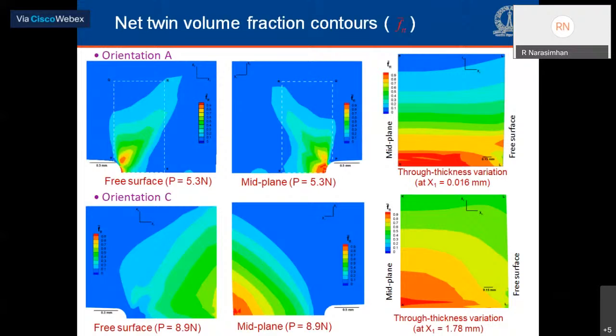And we note again that in A, the C-axis is along the normal to the flat surface of the notch, C-axis along the thickness direction. So if you look at the top panel, you can see that the twin volume fraction is developed in a roughly rectangular region emanating out from the notch root. And there's not that much thickness dependence. If you examine the image on the top right side and the twin volume fraction contours, there's not much variation through the thickness as you go from the midplane to the free surface.